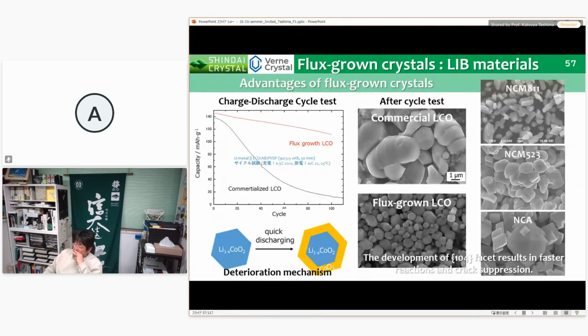Flux-grown crystals exhibit characteristic cycling properties due to the well-developed crystal facets. The degradation mechanism is quite different from that of commercial particles, like these pictures. Upper is commercial LCO, lower is flux-grown LCO.